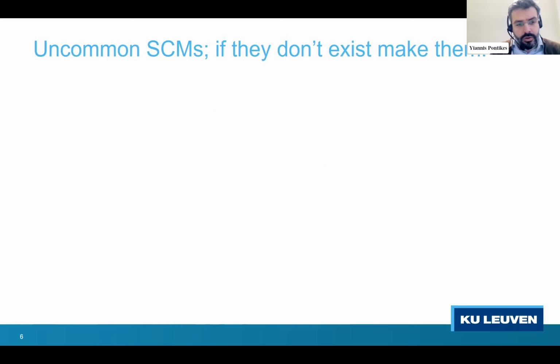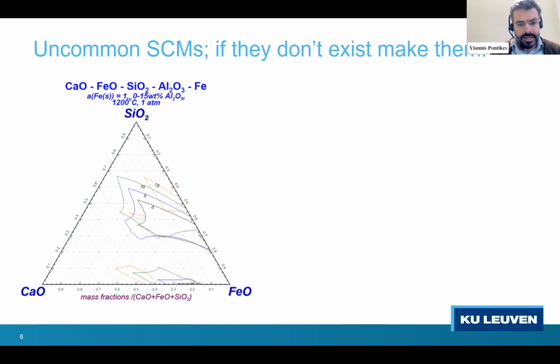So what do I mean by uncommon SCMs? People usually associate cements with calcium aluminosilicates. We see differently. We start from thermodynamics, and you see a ternary diagram. Please don't be intimidated. It basically says that if you are, and I hope you see my cursor, in this region or in this region at 1200 degrees, between calcium, iron (FeO, iron 2), and silica, and the 0, 5, 10, 15 is the alumina content, then your mixture is in a molten state. So successfully, you just made the glass.